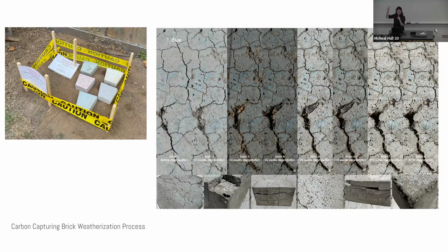And while some images appear darker than the others due to moisture level at the time of capture, the high resolution detail allows us to observe exactly how each unique recipe weathers and mineralizes under stress factors. So this one in particular is a blue brick, and it consists of Portland cement as a base, a bit of CaO, calcium oxide, and biochar.